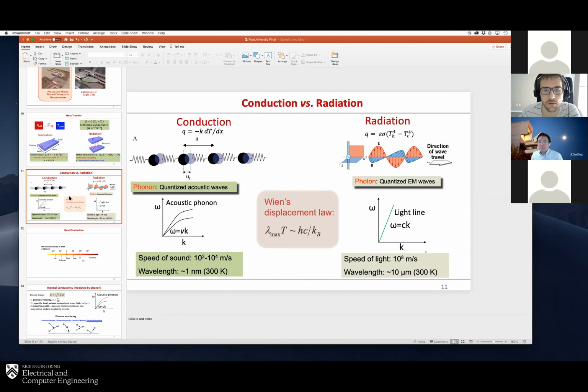In general, it depends on the concentration of defects. Even for amorphous material like amorphous silicon, there are some recent studies, for example, by Alan McGaughey from Carnegie Mellon on phonon dispersion. Strictly speaking, you cannot define dispersion for amorphous material because it's not periodic, it's random. But you can do this with certain approximations. It turns out this dispersion is highly similar to crystalline silicon in the long wavelength limit. However, because of the lack of periodicity, the phonon lifetime, or scattering mean free path, is greatly reduced, especially for short wavelength phonons. So there's some similarity in dispersion between amorphous and crystalline silicon.